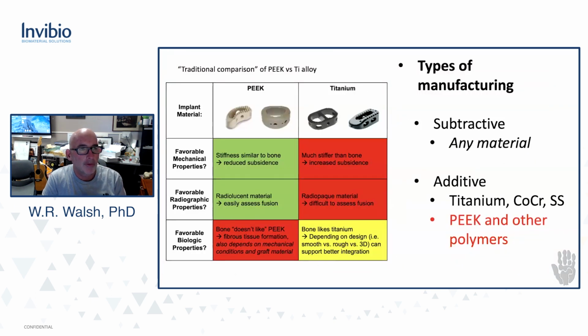And this is a classic comparison of PEEK versus titanium. PEEK is similar to bone. It doesn't muck up your x-rays or your CT scans. But a lot of people think bone doesn't like PEEK. Well, that may not really be true. Bone likes PEEK, depending on the geometry. Ironically, bone does not really like super smooth titanium or super smooth cobalt chrome. We published that 25 years ago. But when it's a little bit rough, when it's a little bit porous, bone can grow into it. We're finding the same thing with PEEK. Bone will grow into PEEK and grab that bone and achieve fixation.